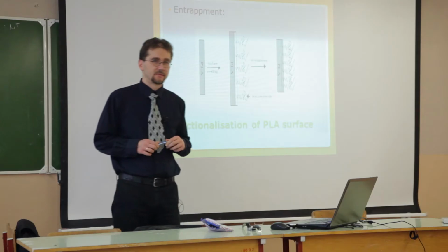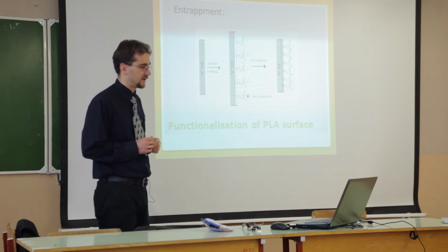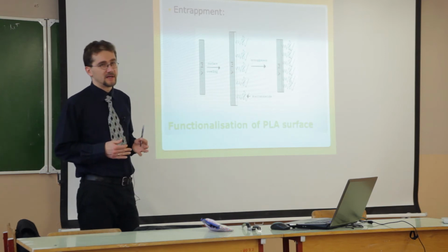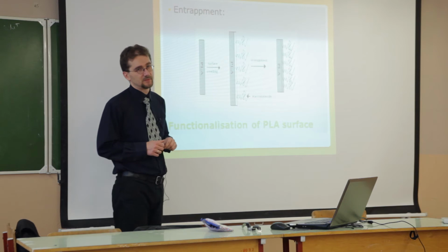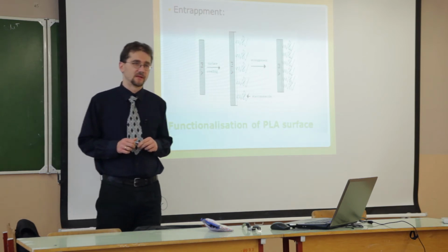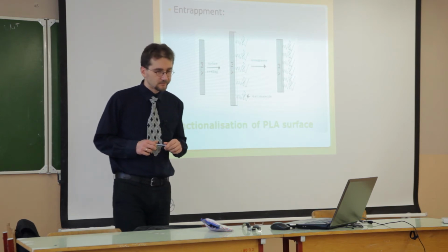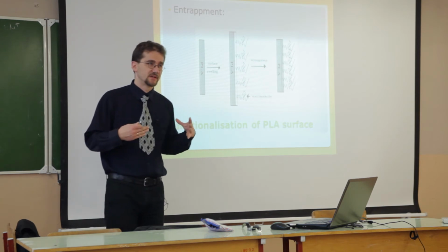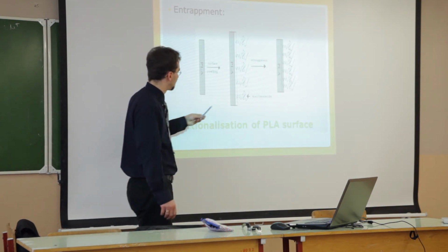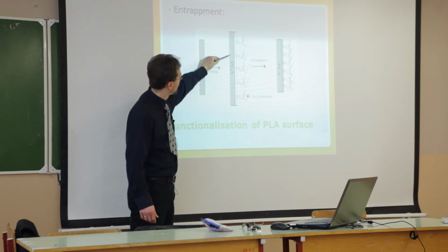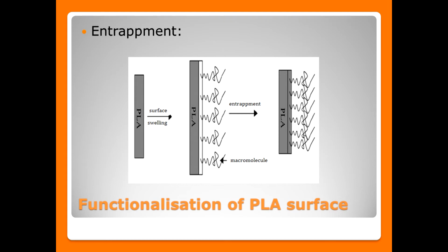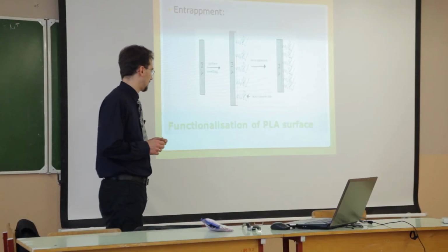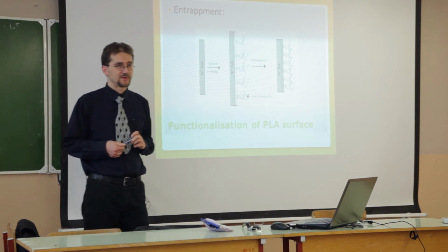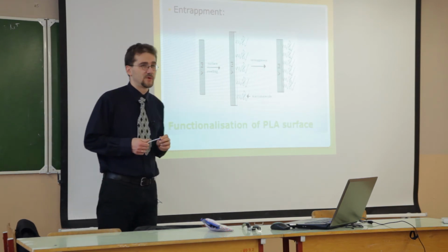Next, the technique I would like to show you is the entrapment process. The idea is that we use a mixture of solvent and non-solvent. This mixture changes the surface, and when macromolecules are close to the surface, their ends can be attached to the changed surface. It can be a swelling process, and afterward we have permanently combined different macromolecules, which can also be an efficient way for functionalization of the polylactide surface.